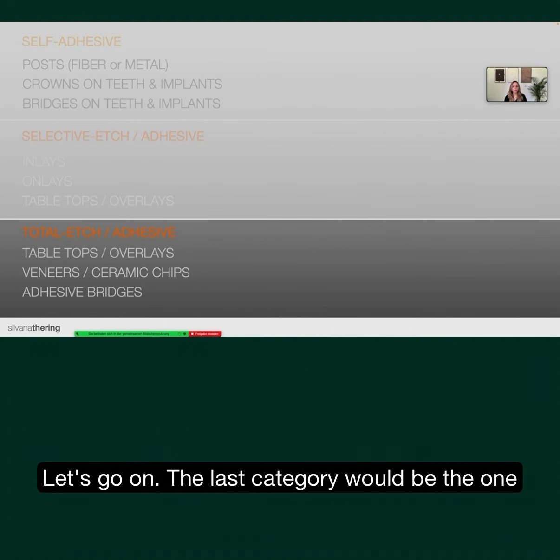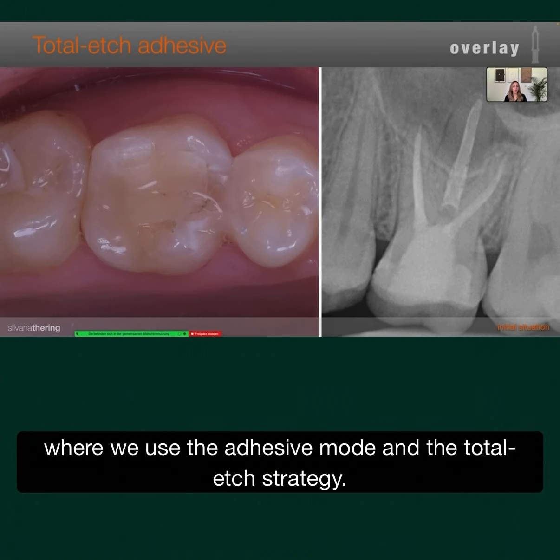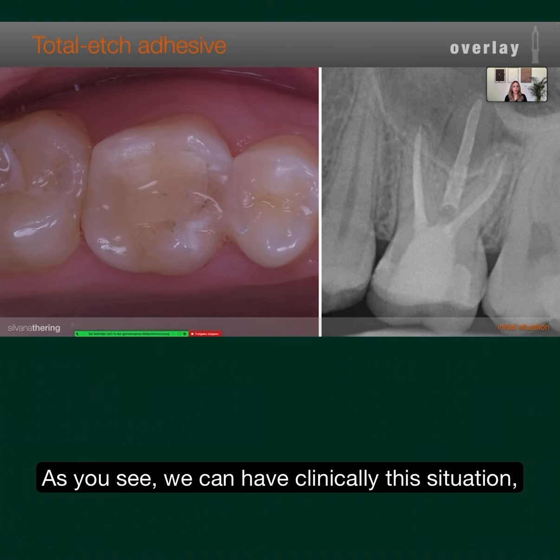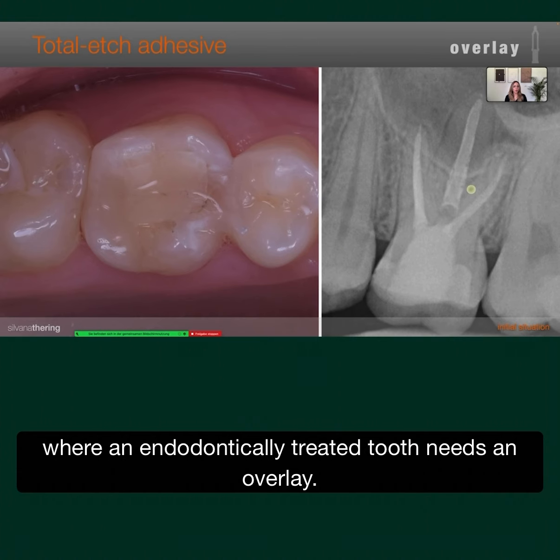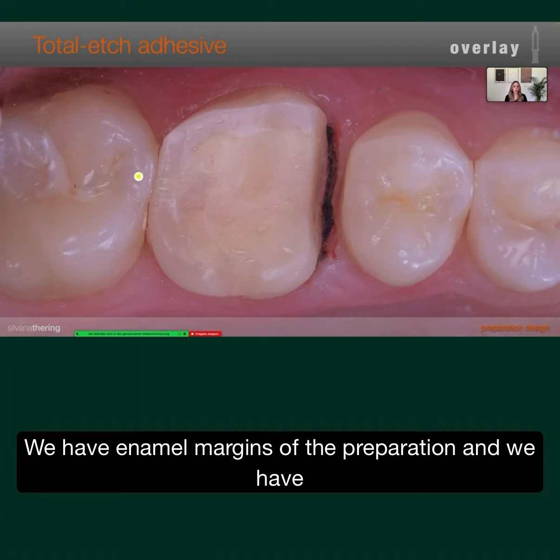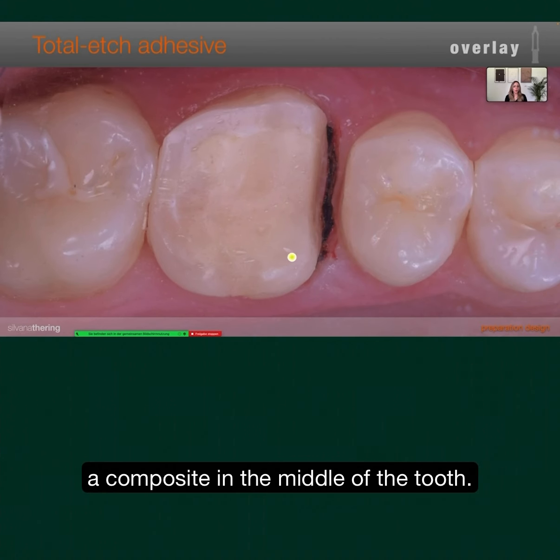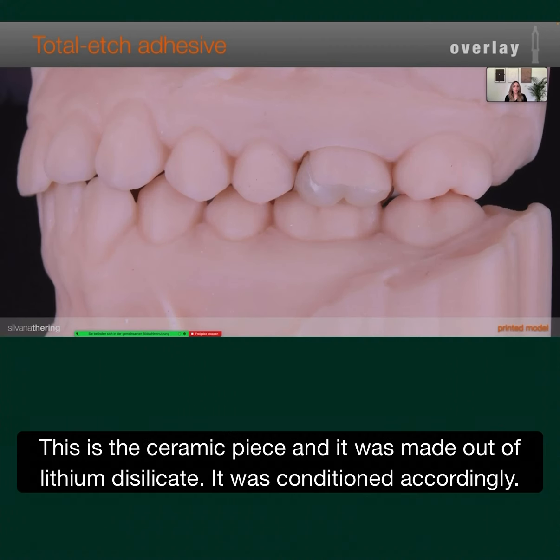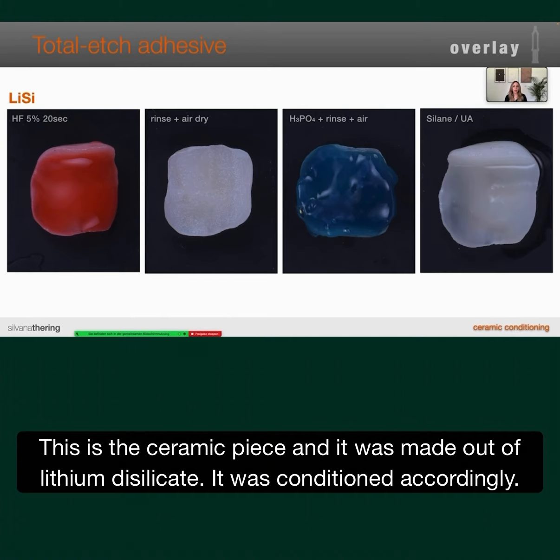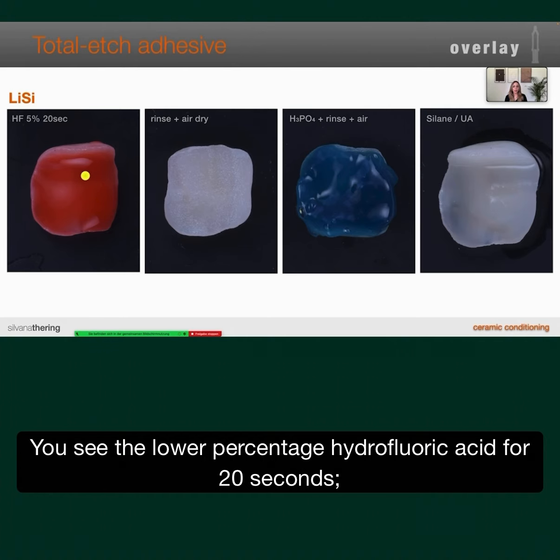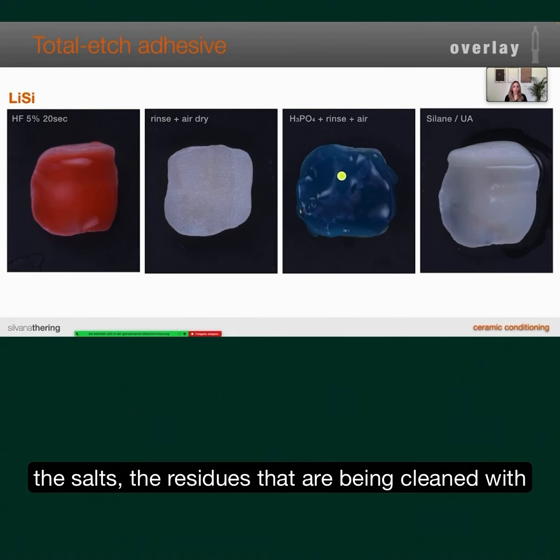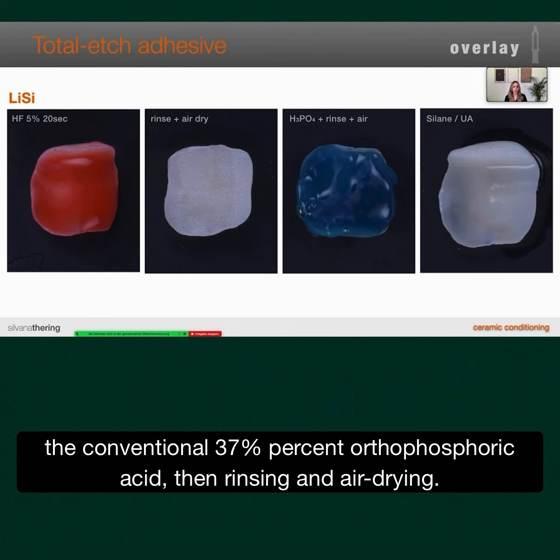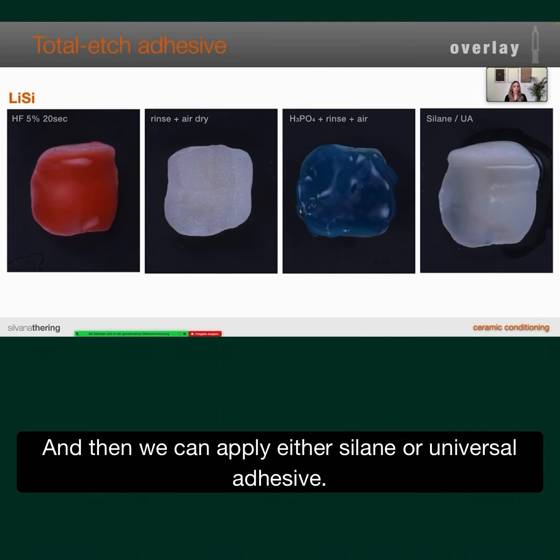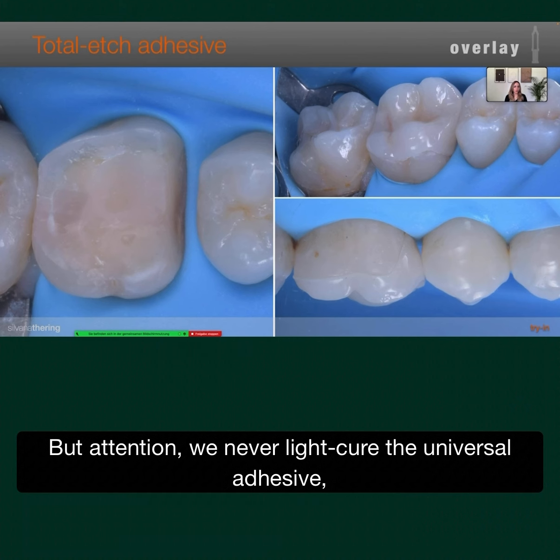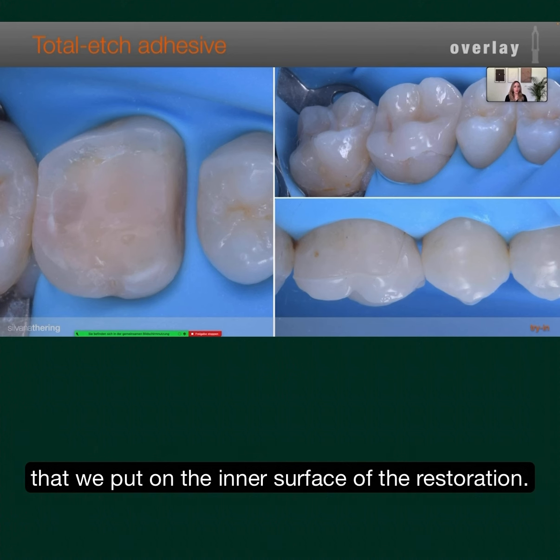So we go on. The last category would be the one where we use the adhesive mode and the total edge strategy. And as you see, we can have clinically this situation where an endodontically treated tooth needs an overlay. We have enamel margins of the preparation, and we have a composite in the middle of the tooth. This is the ceramic piece, and it was made of lithium disilicate. It was conditioned accordingly. You see the lower percentage hydrofluoric acid for 20 seconds. The salts, the residues are cleaned with conventional 37% orthophosphoric acid, rinsed and air dried, and then we can apply either silane or universal adhesive. But attention, we never cure the universal adhesive that we put on the inner surface of the restoration.